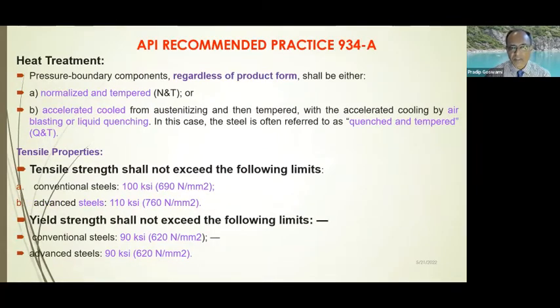Typically, these steels are all normalized and tempered, or they're subject to accelerated cooling from austenitizing temperature, then tempered, and commonly they're called quenched and tempered steels also. So basically we've got two categories of steel, that is normalized and tempered and quenched and tempered. Out of which, to the best of my knowledge, the second category is most preferred for the intended equipment.